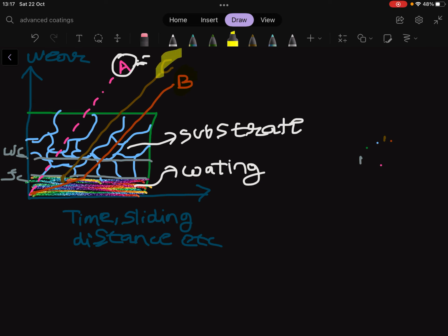Now let's talk about C. So the third condition is encountered when we have premature failure of our coating. So we start again with a lower wear rate behavior given by the presence of our coating, and after a given time we have some failure mechanism, for example detachment of coating fragments. Then we have a very high wear rate, particularly a vertical increase in the wear depth. Then we expose the base material and we might have the same slope as the original curve. Of course, the result is shorter lifetime in comparison to the second condition, that is B condition, because of the premature failure of our coating. In some negative cases, this detachment can produce higher wear rate with a higher slope in comparison to the base material.